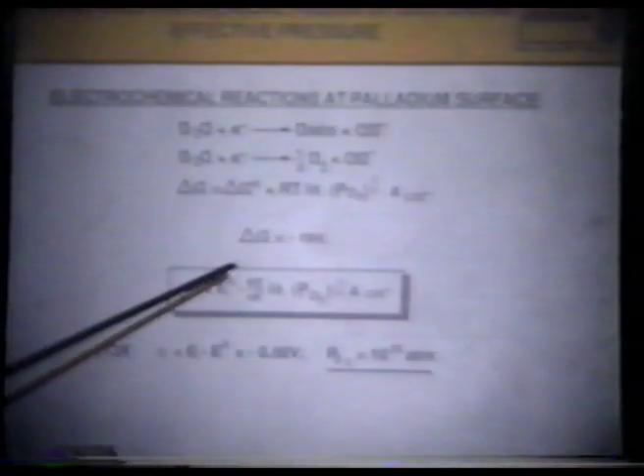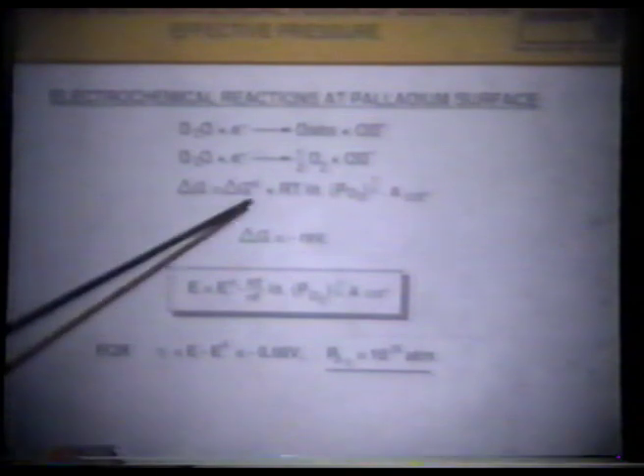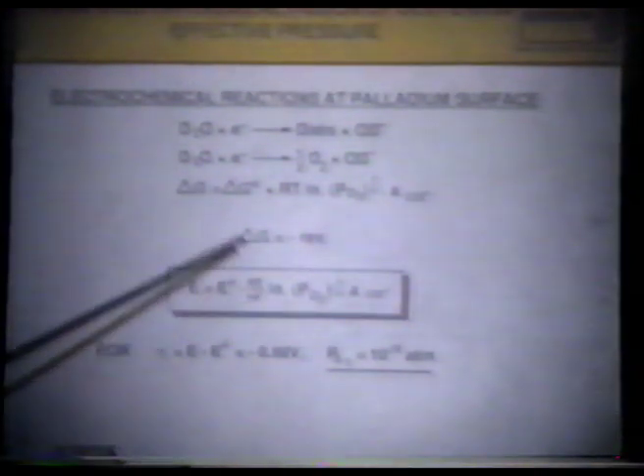One thing about electrochemistry is that you can create conditions that are quite extreme. For example, for the electrolysis of D2O, you go through the free energy relationships and come up with the equation, which is actually a Nernst equation. You can show that for an overvoltage, or potential, of about negative 0.80 volts, if you put that potential in this equation,